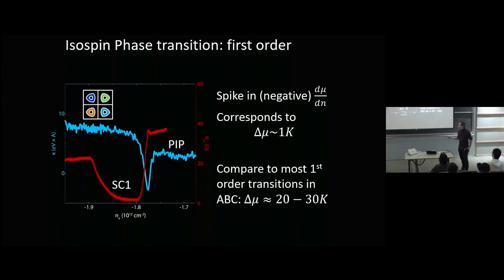I mean, of course, I can't guarantee that the susceptibility to this or that order is not very large on this side of the transition, but every experimental thing that we can say, it looks like the Fermi surface out of which this superconductor emerges just has no broken symmetries, and the phase transition is at least weakly first order. It looks much more like a competing scenario where you're turning up the density of states. As you decrease the density, you're approaching this Van Hove singularity, you get superconductivity first, and then you get Stoner, and then of course everything is different and you don't get superconductivity again.